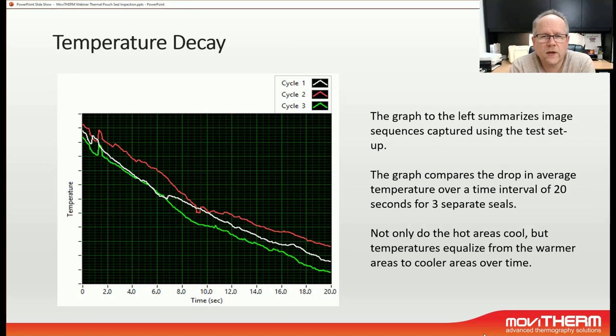So the next test that we have performed on this bagging line is a temperature decay test. This is to monitor the temperature decay over time in the same spot on the sealing area. This will tell us how the temperature cools down and at what rate. In this instance, we have used 3 bags, selected a region of interest on each bag, and essentially monitored the temperature decay over time. And these cycles 1, 2, and 3 are different bags.